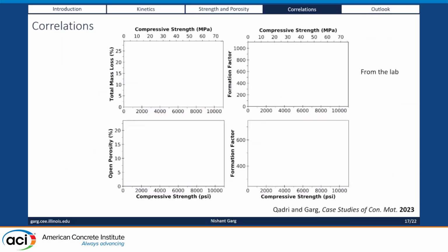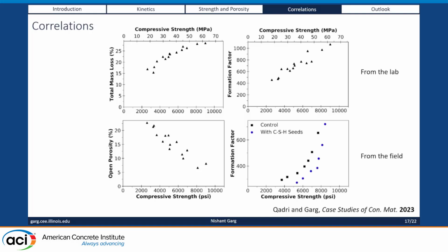So again, a bunch of other correlations. These are correlations between techniques which people have already explored. So whether it's the mass loss from TGA, or the formation factor, porosity versus strength, as well as the formation factor versus strength. Again, these are standard correlations one would expect. And again, we had to do this. This is also out last year.